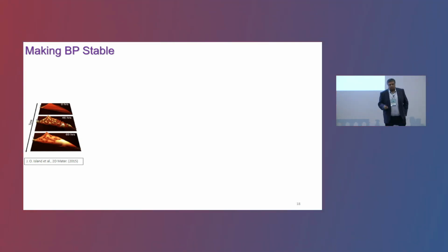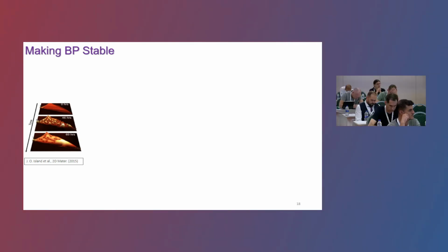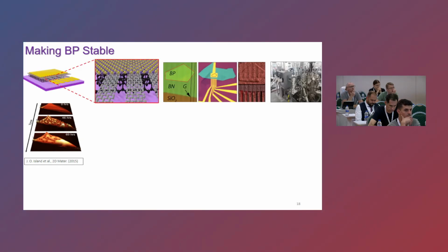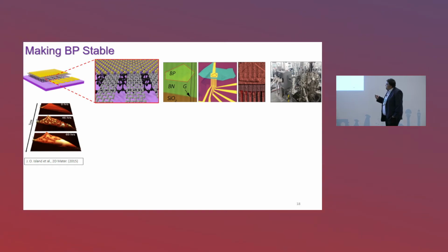If you exfoliate the material here and then just leave it on the table, this is a relatively thick crystal. If the material is below 5 nanometers, it will degrade completely within half an hour. As you can see, the material is pristine, and whenever we expose it outside, it really just dies. So as a first step, we tried to develop a transfer setup in a glove box environment